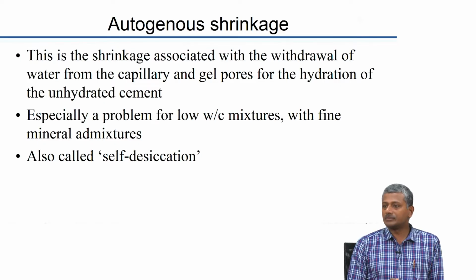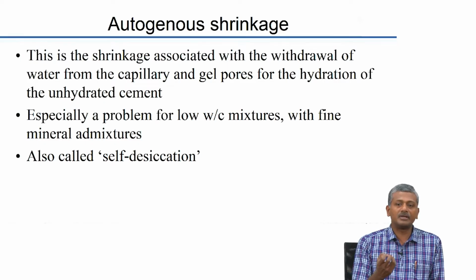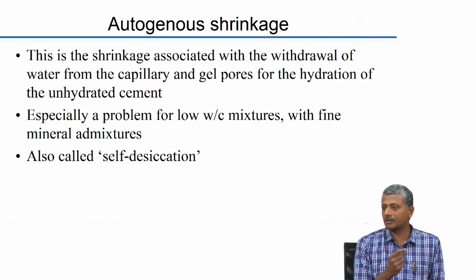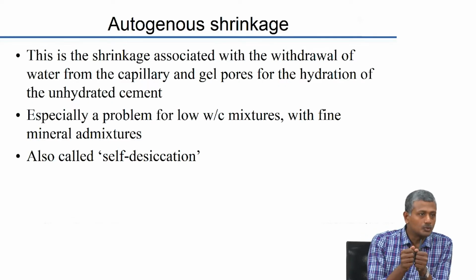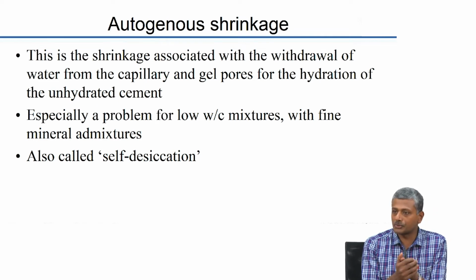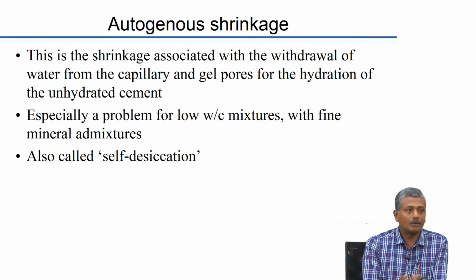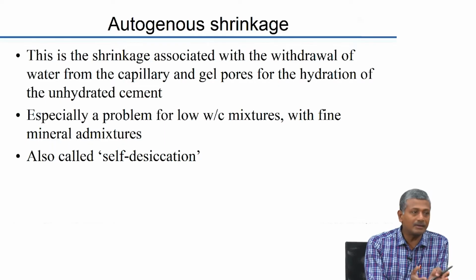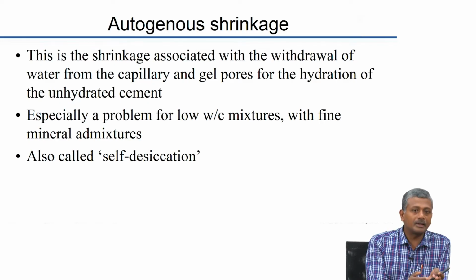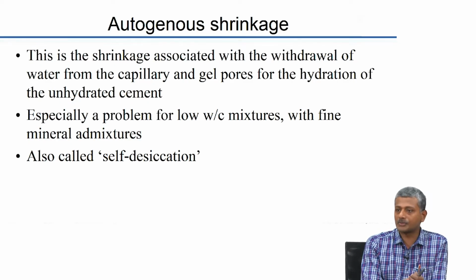Okay, one of the aspects that you need to think about is not all of the cement inside the concrete gets hydrated. Some cement remains unhydrated and it starts pulling the rest of the water towards it for undergoing hydration, and this water now has to travel through porosity which has been reduced because of hydration of other cement particles. So, whenever there is travel of water through thin pores, there is going to be high capillary pressure associated with it, that causes shrinkage. Alternatively, you can also think about the fact that the unhydrated cement, when it reacts with the water, there will be a chemical shrinkage associated with it that will also correspond to overall self desiccation or self drying of the system.